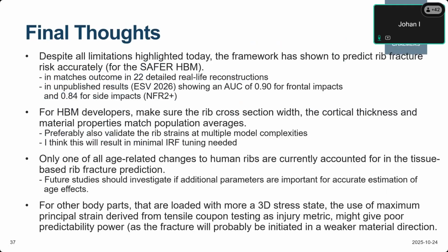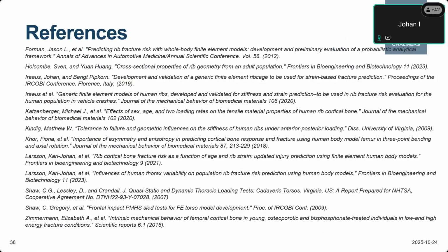For other body parts that are loaded in a more 3D stress state, we could see here that we had the maximum principal strain aligned along the osteon direction in the rib. So that's more or less a 1D stress state. But if we have a more complex structure with 3D stress states, the pelvis for example, then using the maximum principal strain derived from tensile coupon testing as an injury criterion might give poor predictive power. The reason is that the fracture will probably be initiated in one of the weaker material directions. And here are the references, and that was all for me.